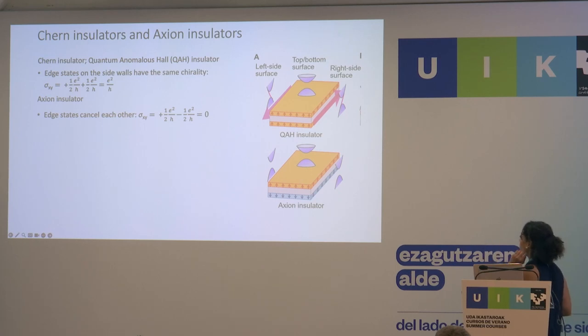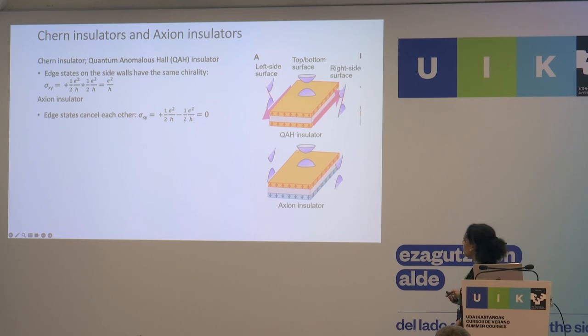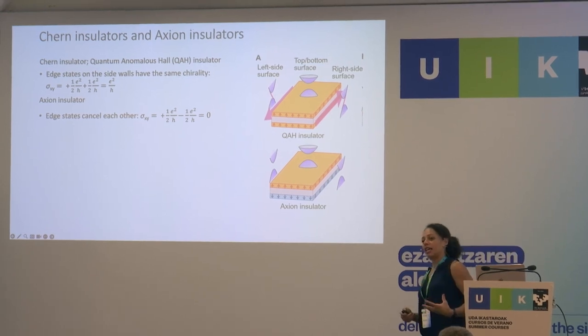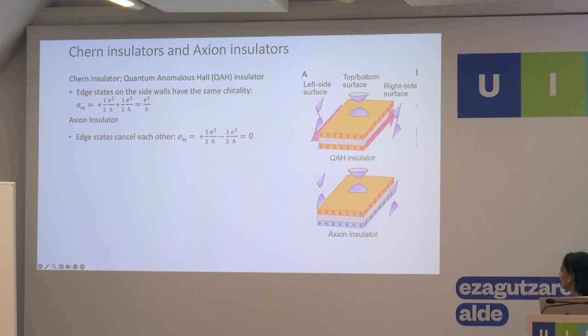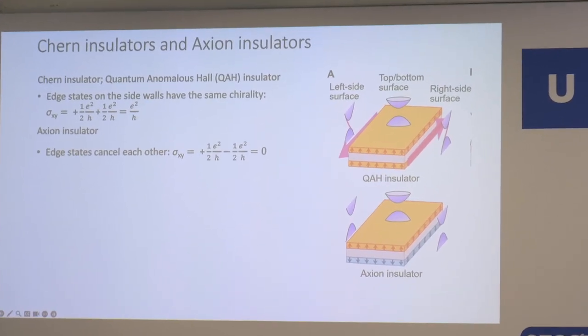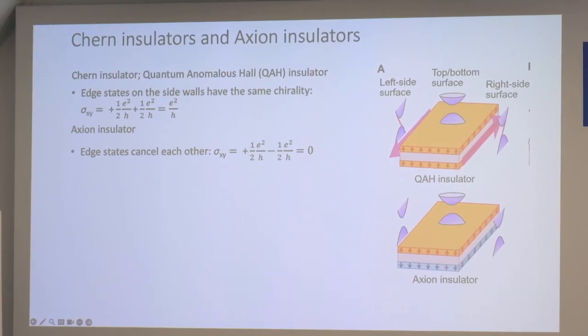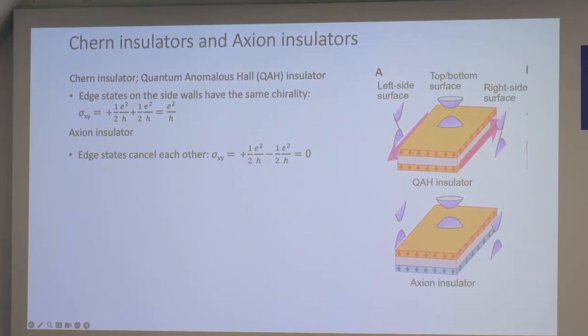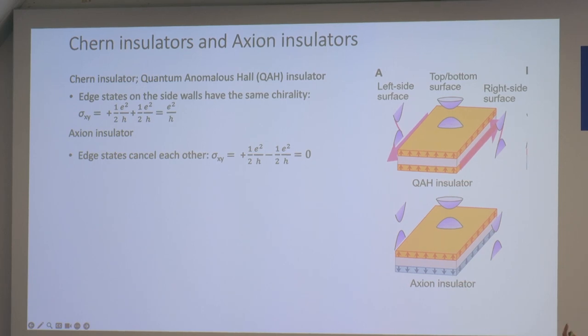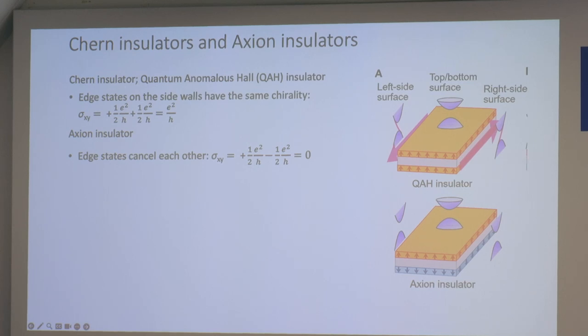And of course, now people are looking at what happens when you take, in the one case, the quantum anomalous Hall insulator where the surfaces have the same magnetic orientation. If you take the antiferromagnetic analog of this, you get an axion insulator. To physically create this sort of state, it means that you have to create magnetic moments that have opposite directions on the top and bottom layers. So this can happen by proximity coupling to different orientations of magnetism, or by carefully doping the systems so you can get different orientations of magnetism here.